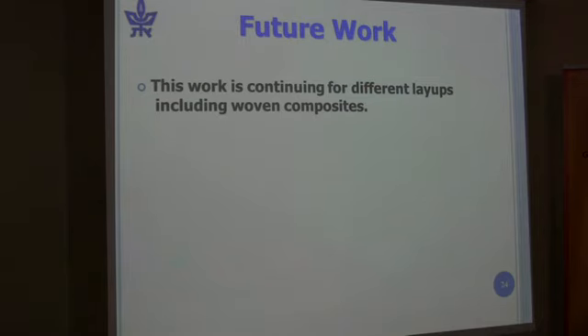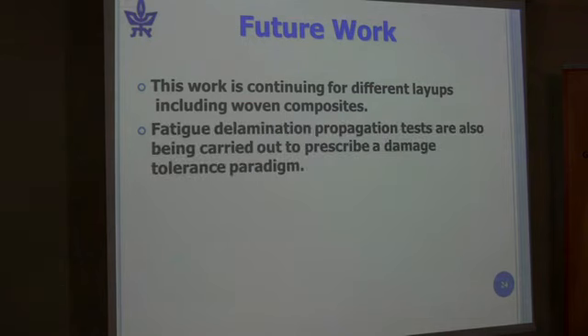We're working on woven composites. We've done DCB specimen testing using woven composites. Someone showed us, I think, DCB testing here yesterday, and so we're getting G1C values. We're also carrying out fatigue delamination propagation tests. We've done this also with some woven composites with DCB, and we're going to be starting to work on mode 2 and mixed mode in these directions,